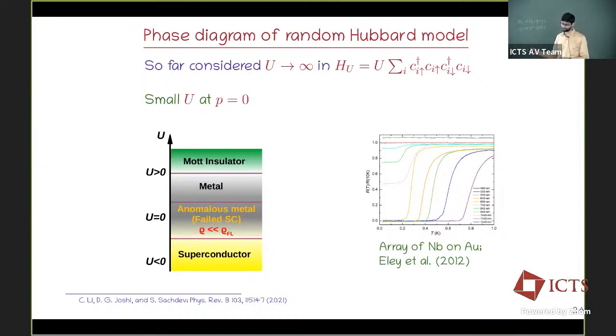It's basically the absence of quasiparticles. That's what we show, that there is really a transport by some pair fluctuations, and there is a Bose metal kind of phase that actually controls this residual resistivity in this case, and it enhances or reduces the resistivity compared to the Fermi liquid. So there is a transport by these pairs of electrons. These fluctuating pairs do not completely become coherent and condensed to give you superconductivity, but nevertheless they contribute to transport alongside your electrons such that you have enhanced conductivity in this phase.